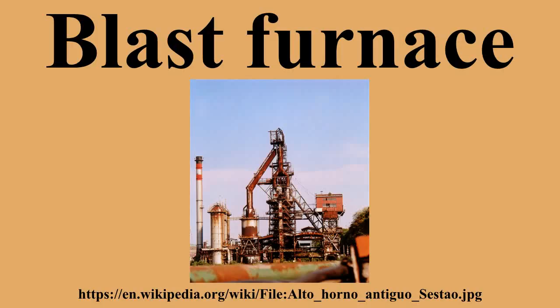The tuyeres are used to implement a hot blast, which is used to increase the efficiency of the blast furnace. The hot blast is directed into the furnace through water-cooled copper nozzles called tuyeres near the base. The hot blast temperature can be from 900 degrees Celsius to 1300 degrees Celsius depending on the stove design and condition. The temperatures they deal with may be 2000 degrees Celsius to 2300 degrees Celsius. Oil, tar, natural gas, powdered coal and oxygen can also be injected into the furnace at tuyere level to combine with the coke to release additional energy and increase the percentage of reducing gases present, which is necessary to increase productivity.